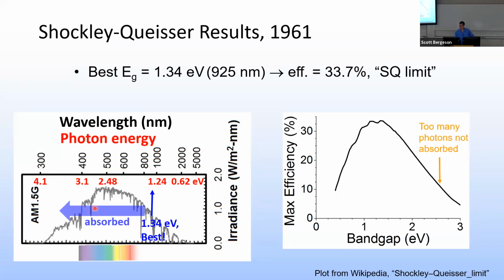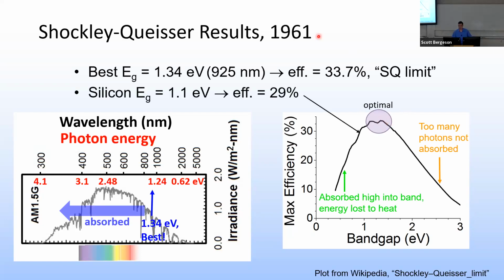You don't want a higher band gap energy because, as I mentioned, then a lot of your photons won't be absorbed. And you don't want a lower energy because your electrons will be kicked too high into the band and you'll lose energy due to heat. So this is kind of the sweet spot right here. And it turns out silicon is not too far away from that sweet spot.